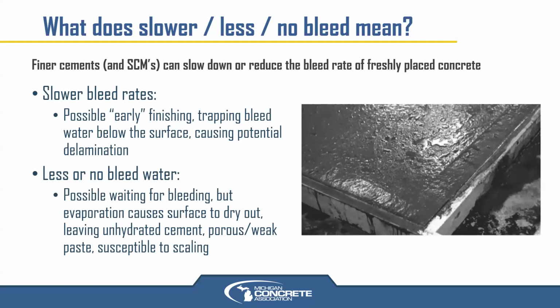And then what happens is, especially on exterior placements, even if it's an interior slab, but it just doesn't have the building around it yet for control of wind speed and moisture and temperature, or if it's an exterior placement, this is always a concern in exterior concrete. Evaporation can occur, and then that lack of bleed water to replace any water that's evaporating from the surface allows that top surface to dry out, leaving unhydrated cement particles, which means weak. If it's not hydrated cement, it's literally just a chunk of powder. It hasn't turned into that glue that glues concrete together, right? So if you don't have the water to chemically react with the cement, then that unhydrated cement is weak.